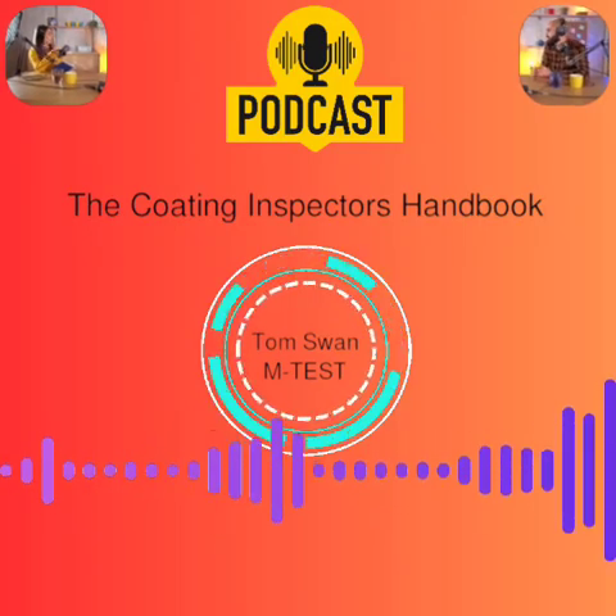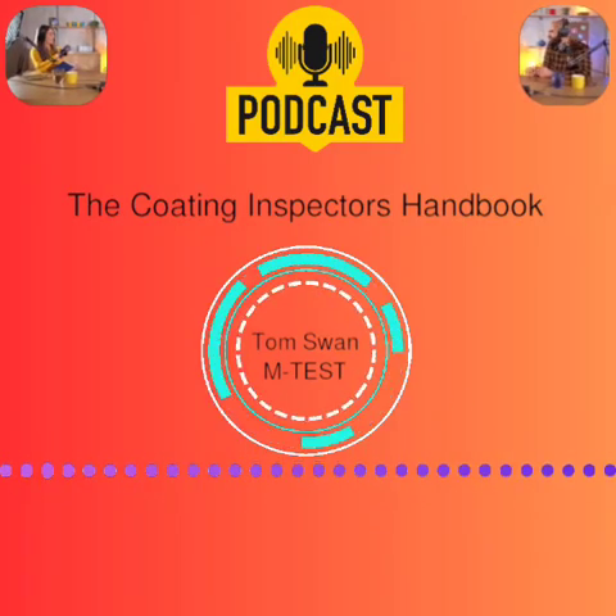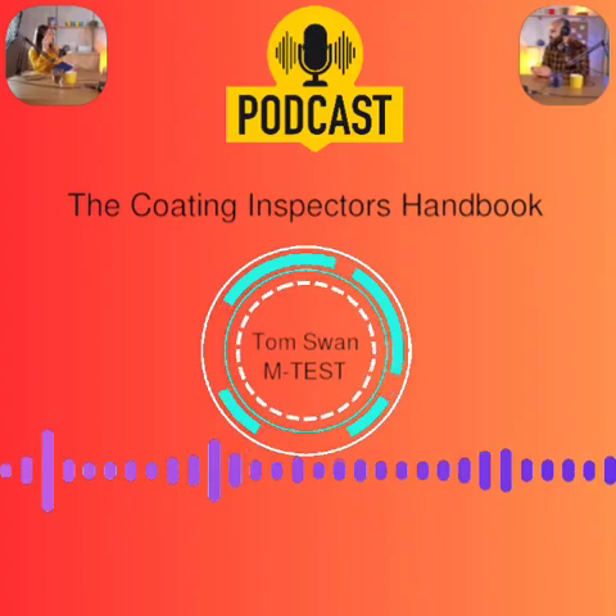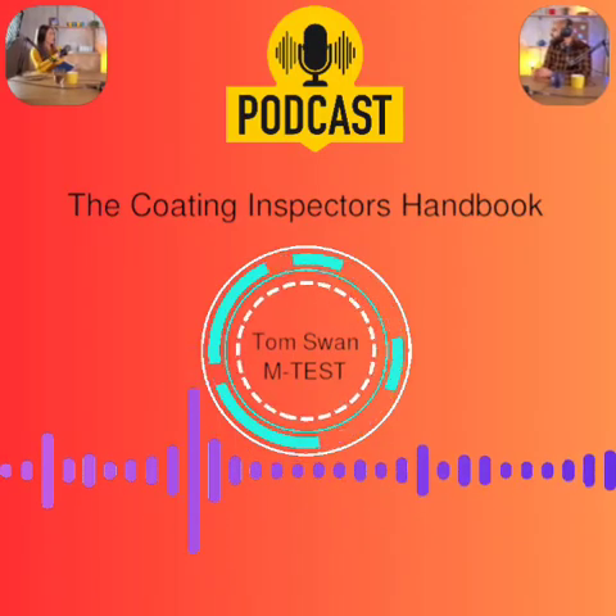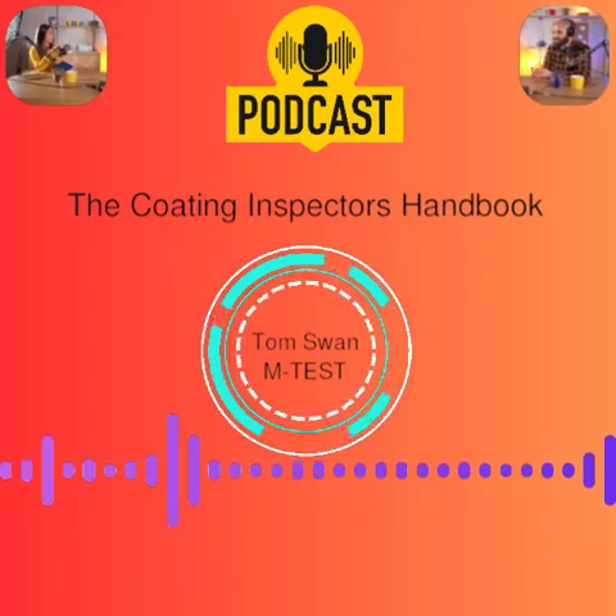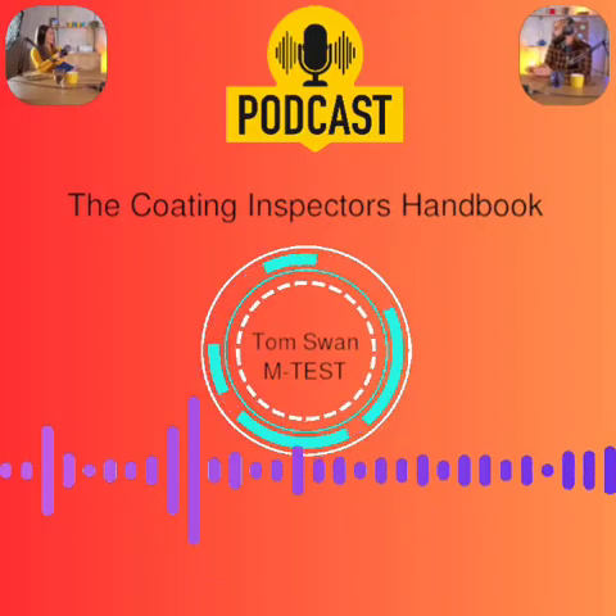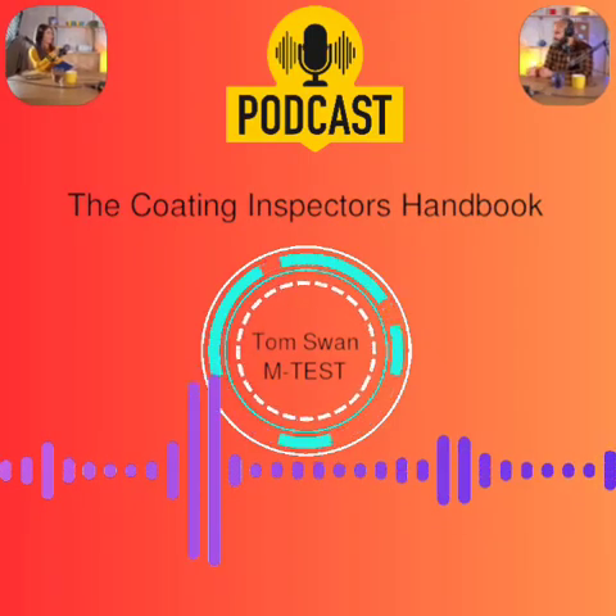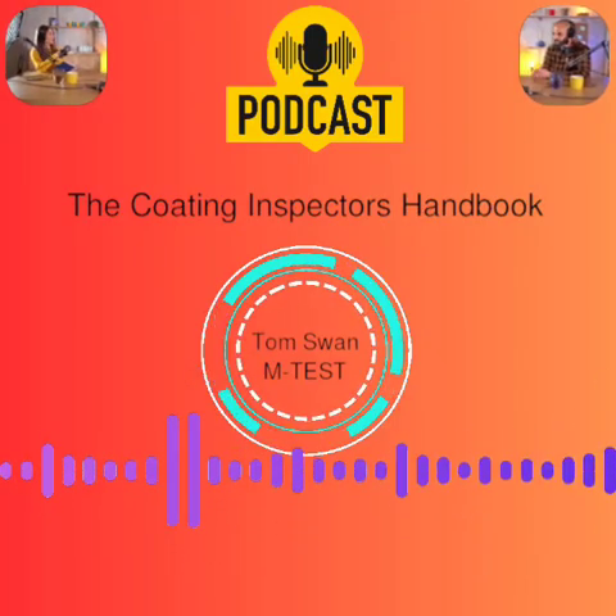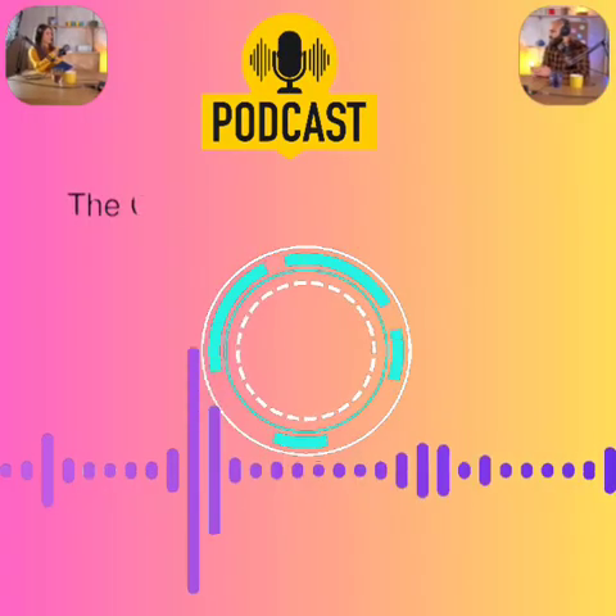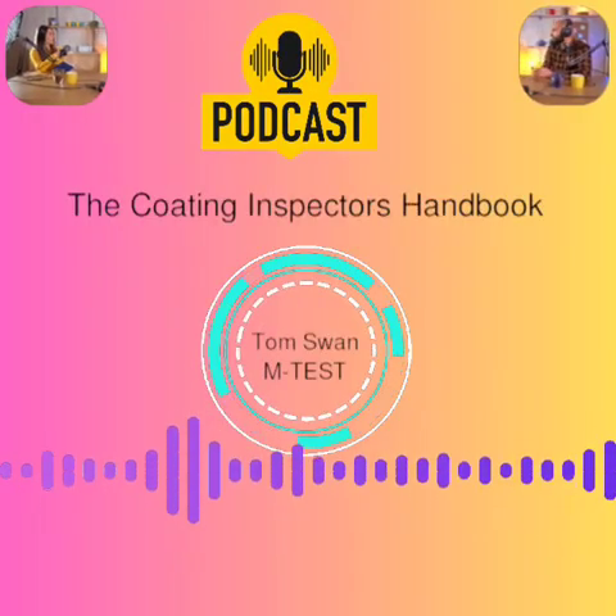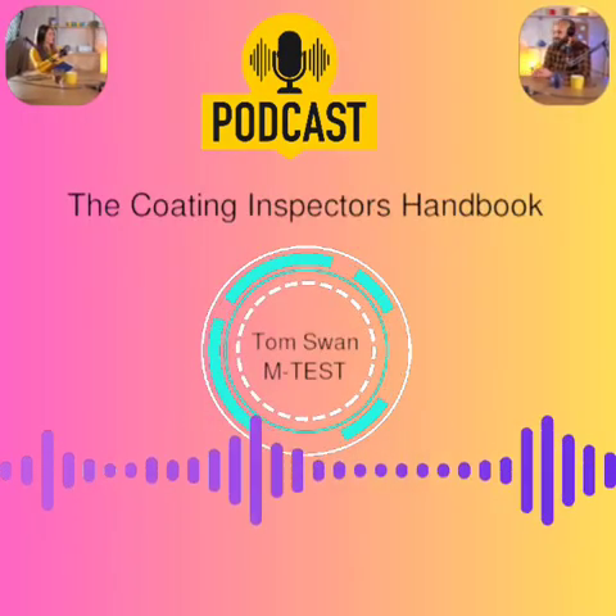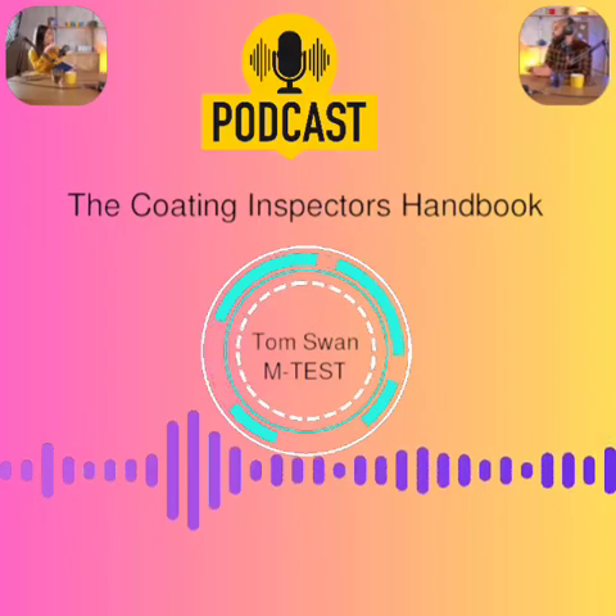Important warning, though. High voltage testing can damage the coating if you use too much voltage or go too slow. Know what you're doing. Let's talk low voltage first, under 20 mils on metal. Standards like ASTM D5162, NACE RP0188. Voltages vary. ASTM uses 67.5 V. ISO uses 9 V or 90 V. A tester where you can adjust voltage easily is handy.